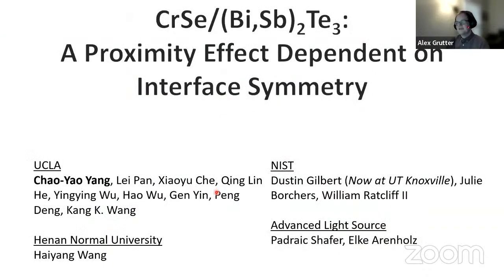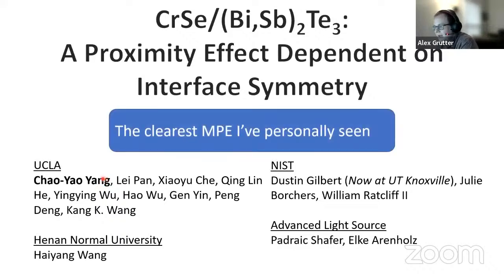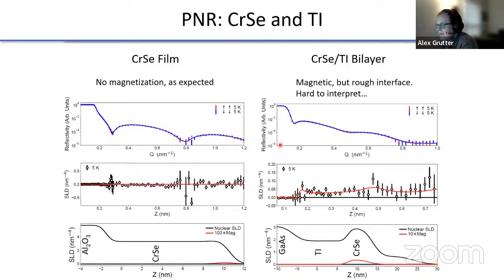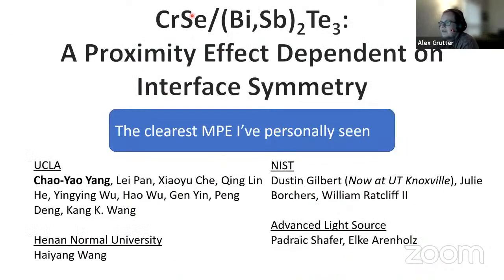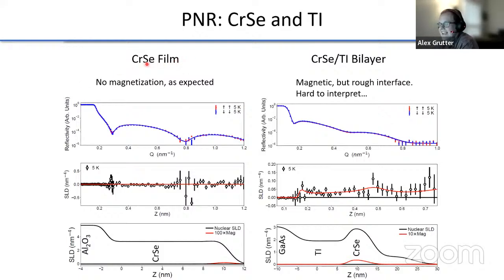Now I want to show you an example of a system where we are relatively confident that we dotted all our i's and crossed all our t's, and we have a real magnetic proximity effect. This again was done in collaboration with Kang Wang's group and led by Chaoyao Yang. I think it's the clearest example of a magnetic proximity effect that I've seen personally. What we're doing is using chromium selenide. Now, chromium selenide is an antiferromagnet.